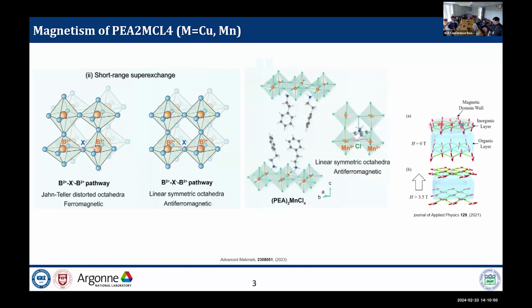Next is PEA2 manganese tetrachloride. This is a quasi two-dimensional Heisenberg antiferromagnetic material. The magnetic ordering comes from the manganese and chlorine, with superexchange interaction between manganese ions from here, a linear symmetry octahedral antiferromagnet. Also, similar to copper, manganese has a distorted octahedral D4h state, but different from the copper case, manganese has only five electrons in the d orbital,